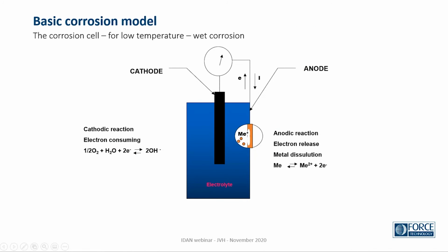I was also asked to say a little about corrosion and the effect from welds on corrosion. And to start with corrosion itself, it's a process where we dissolve a metal. And to have that process running, the electrons formed in this process need to be used in another process. Otherwise, it will stop after some time. It would be saturated in the electrolyte in the environment here, and will almost go to a stop. But if we have another process which is using the electrons, then we have the corrosion cell going on.